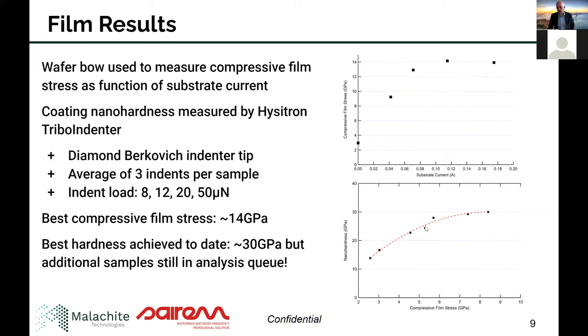Clearly, we have other coatings here that have gone higher in film stress than 8.5 GPa, and hopefully by the time this presentation airs we'll have the remaining hardness results. The dashed line indicates the trend of coating quality, and it looks like it might be plateauing — it may not just keep going up with film stress. One theory here at Malachite is that because we're ionizing argon and using that as part of the ion assist, we may be getting argon incorporation in the film, which could be leading to this rollover. Data is yet to be presented, but we can certainly discuss this application after the meeting.